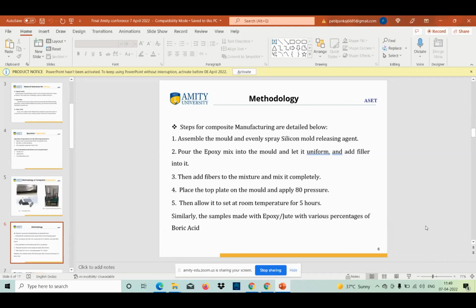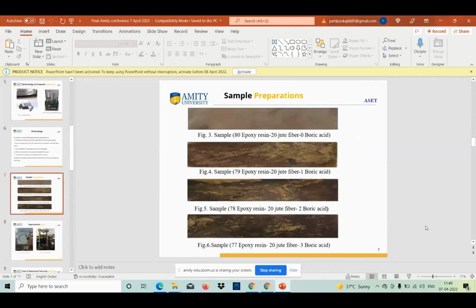the same test will be made for the epoxy jute fiber with various percentages of boric acid. We will carry out four different concentrations of boric acid. 0% boric acid will be used for the first sample, 1% boric acid for the second sample, 2% boric acid for the third, and 3% boric acid in the fourth sample. The jute fiber is at the same percentage, that is 20%. Only the epoxy resin will change, meaning 80%, 79%, 78%, and 77%.